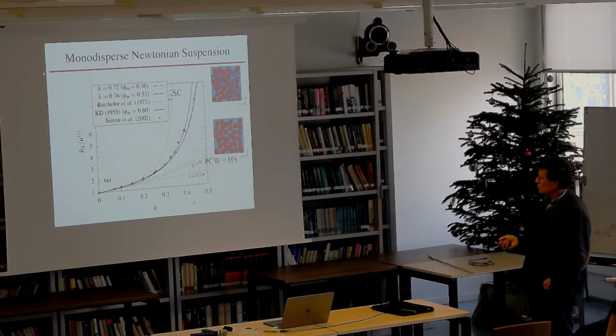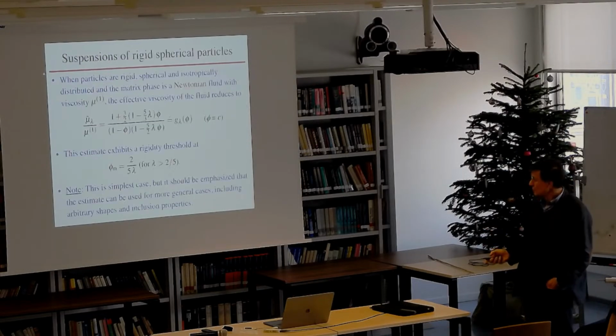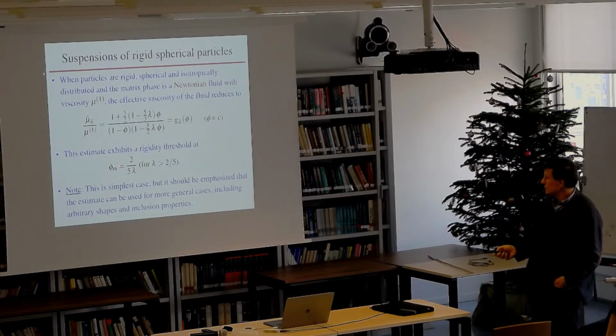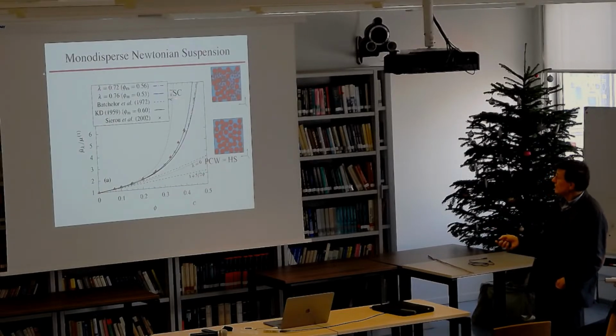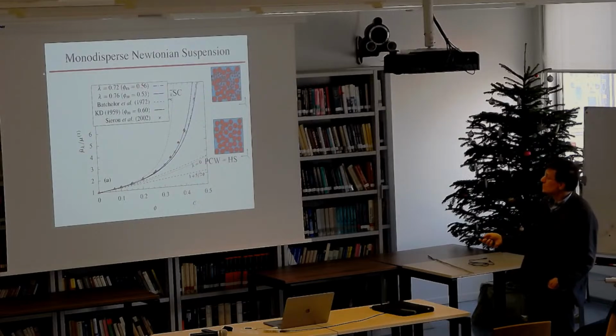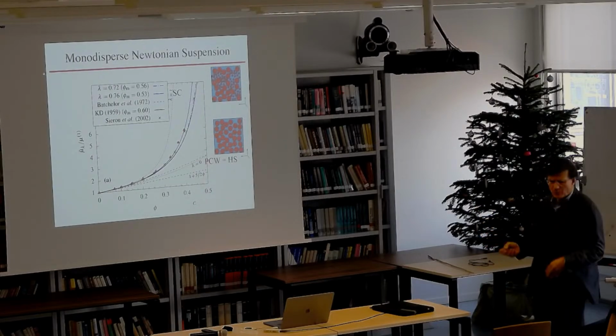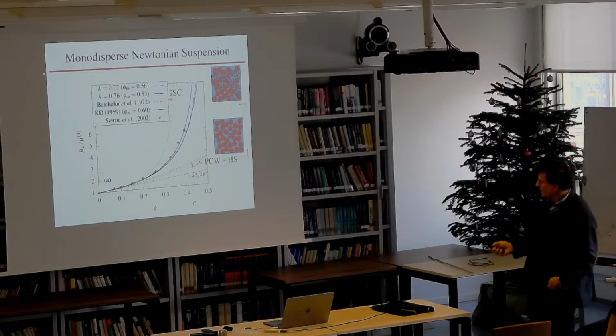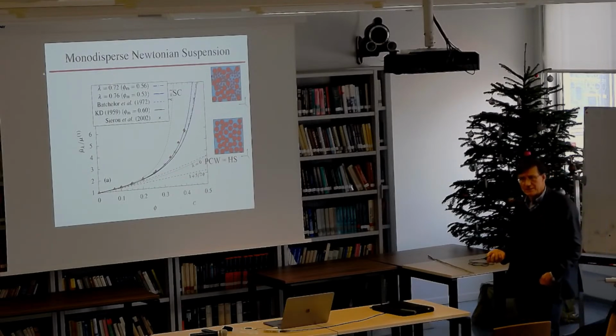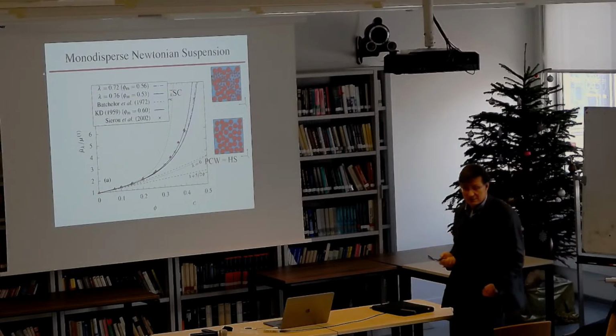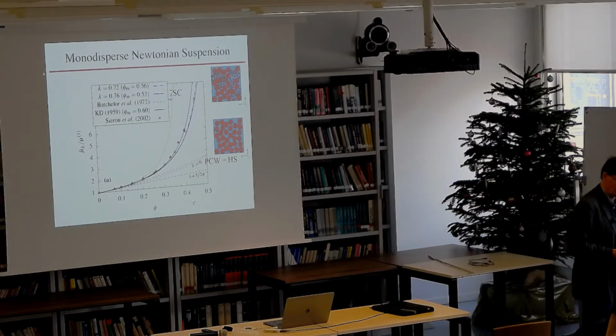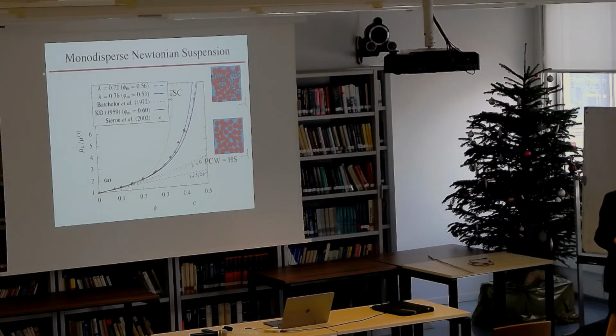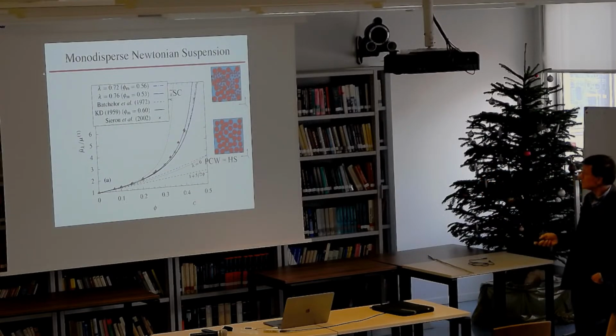The particles carry all the load, and the suspension or composite cannot deform anymore. So if for a given microstructure you have an idea what the percolation limit is, you can use it to choose lambda from this expression. It turns out that lambda equals 0.72 gives you 0.56, which is close to it. It's a complicated problem, and experimentally it's difficult to measure this rigidity threshold, also because when particles start coming into contact, friction effects become important, and that's something we're not accounting for here.